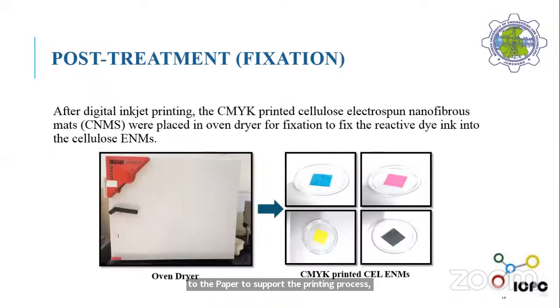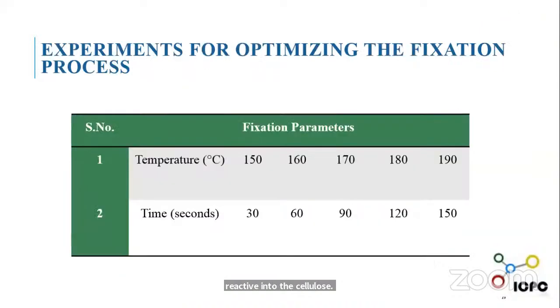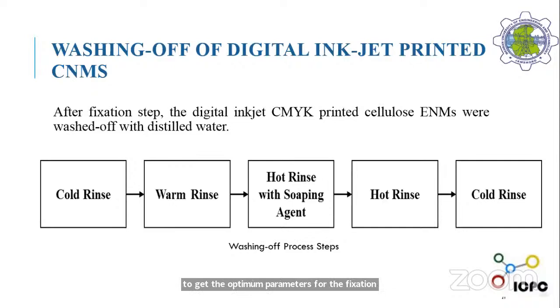After printing, we do post-treatment fixation. After digital inkjet printing, the CMYK printed cellulose electrospun nanofibrous mats were placed into the oven dryer for fixation to fix the reactive dye into the cellulose nanofibrous mats. For post-treatment, we also optimize parameters such as temperature and time for fixation to get the optimum parameters for the fixation process. After samples were fixed, washing was done to remove the unfixed dye, unfixed reactive inks, from the printed samples of cellulose electrospun nanofibrous mats.